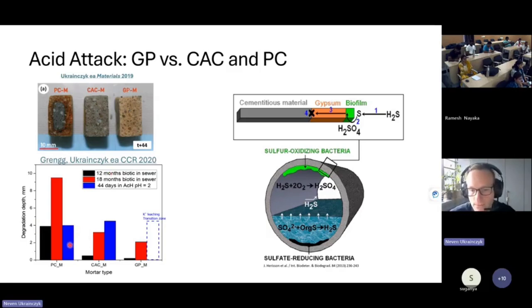And you can see this here. We had actually the PC mortar was the worst material we could use. There were some Portland cement mortars, and you can see here after 18 months the degradation depth is very high. We compared it also with calcium aluminate cements because those are actually the real durable materials for sewers. And here are the geopolymers, which actually outperformed all those materials. We only had the leaching of potassium, but this was not detrimental for the strength or the coating performance.